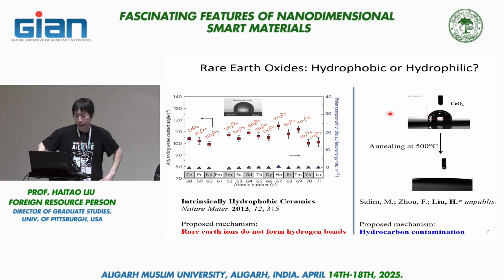So when they discovered this hydrophobic ceramic material, which is a series of rare earth oxides, it was quite exciting because a lot of other hydrophobic materials are not thermally stable, but these seem to be thermally stable. However, if you think from a chemistry perspective, this is very counterintuitive because ceramic materials are highly polar. You have negatively charged oxygen, positively charged metal ions. How could those be hydrophobic? It doesn't make any chemical sense. Now, when we look at this, we quickly realize that this is just another example of airborne hydrocarbon contamination.